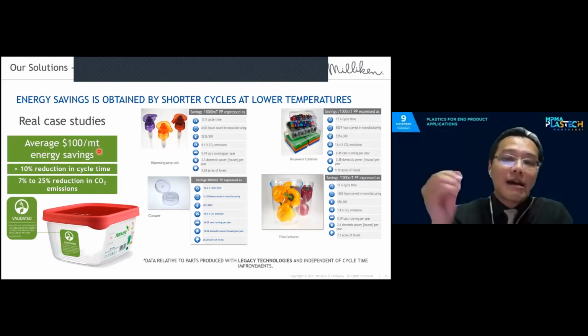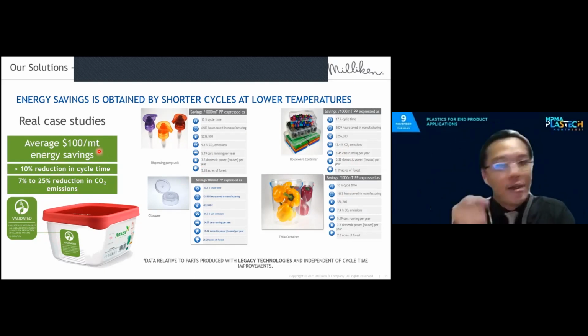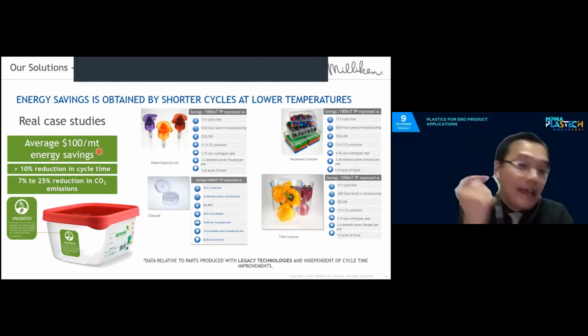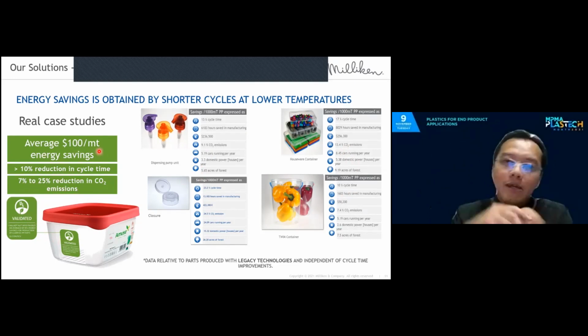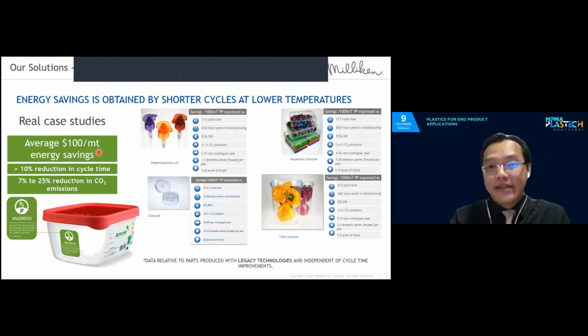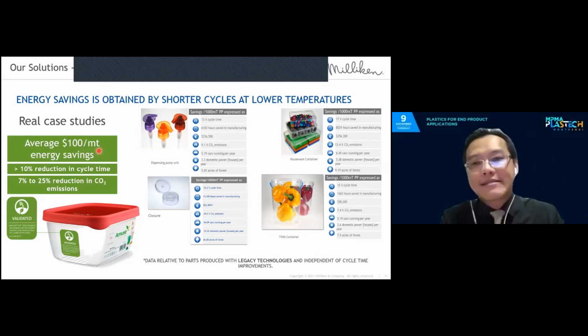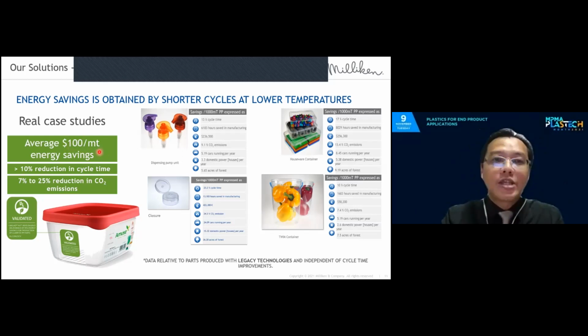But don't forget, if you calculate the dollars and cents, if you put in your energy costs, your overhead, your labor costs, your depreciation, and you put it all in, a 10% reduction in cycle time with the productivity that it brings can sometimes bring up to an average of $100 per metric ton of dollars savings, right? And this is pure processing optimization. It's not talking about getting a cheaper material, but with NX8000 clarified RCP, optimizing the processing conditions alone gives you dollar savings as well.